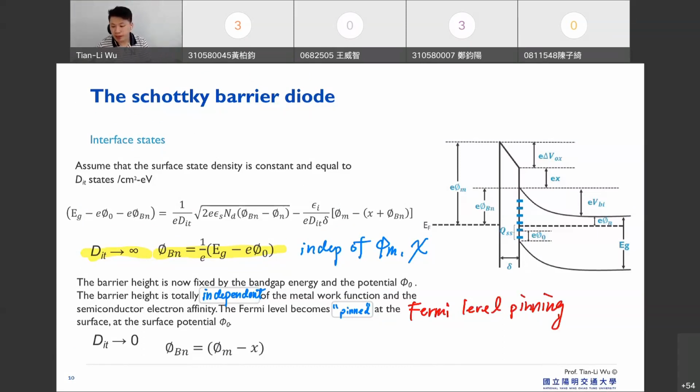One more thing I want to mention: the concept of interface state and Fermi level pinning is a little bit advanced. When you have several years of experience in semiconductor device measurement, reliability, or fabrication, you will find that the interface always creates lots of issues, and most of the issues are related to the interface state. If the interface state is too large, that creates what we call the Fermi level pinning. And this Fermi level pinning leads to the problem that we are not able to